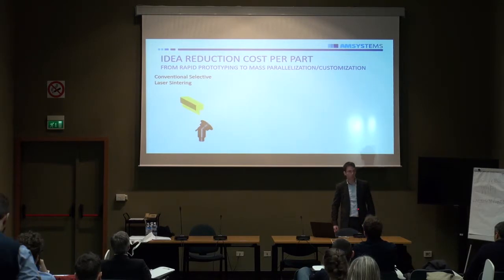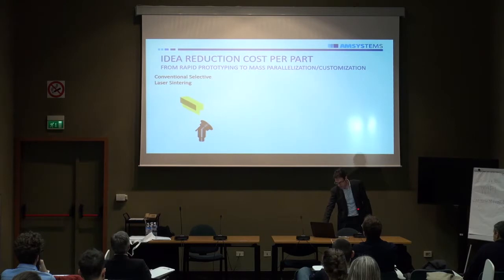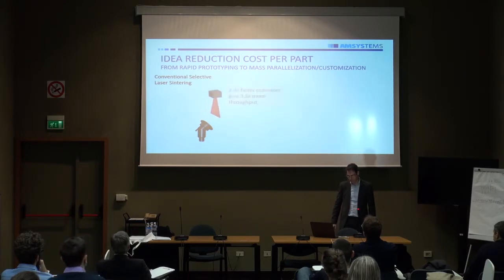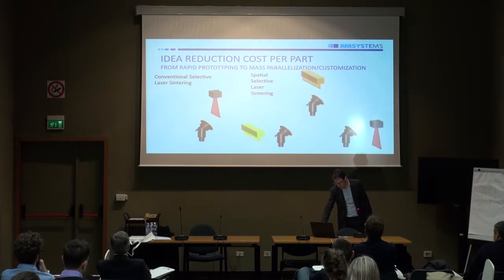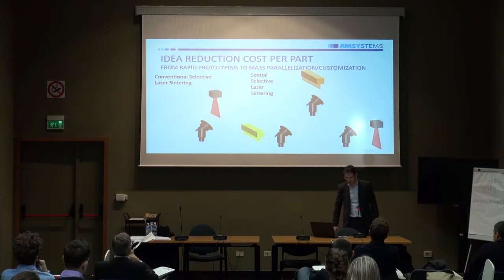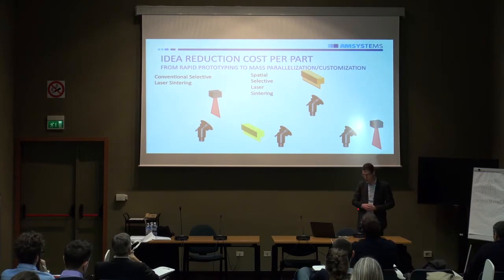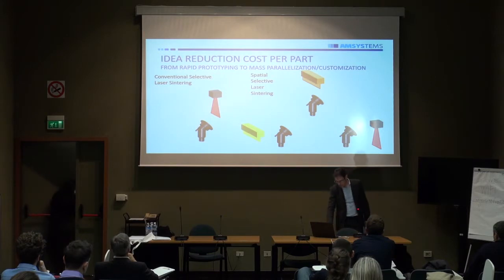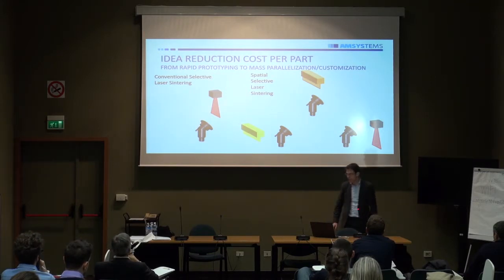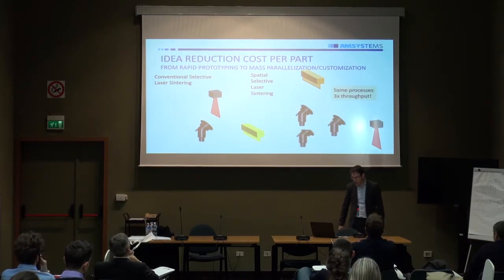And of course you can make these process steps quicker. For example, if you make the process steps 3.3 times quicker, the process is 3.3 times faster, as you can see here. But what we work on is not having one build chamber and moving your processes over the build platform, but having your processes fixed and moving your build platform from one process to the other. And what you see here is these 3 process steps next to each other, and then we have 3 build chambers in this example. And the build chambers are moved from one process station to the other.